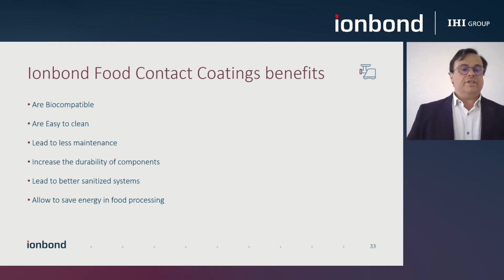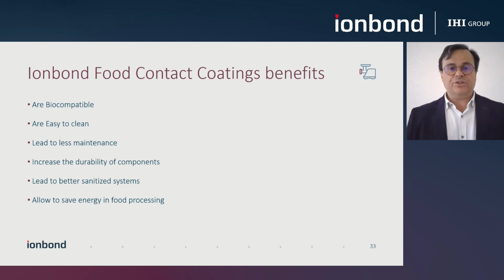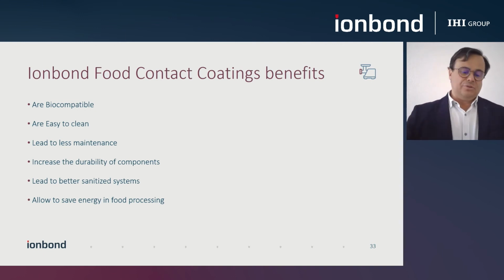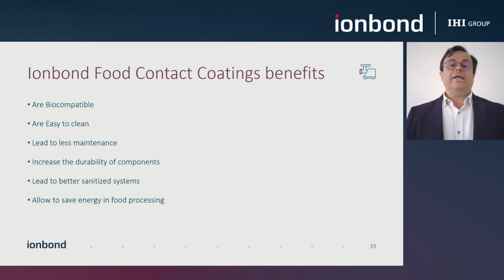In summary, we have seen the coatings are biocompatible, they are easy to clean, they lead to less maintenance in the systems where they are applied, they increase the durability of the components indeed. Overall, you have a situation where you have better sanitized systems where even the bacteriological proliferation is going to be reduced by the use of these inert coatings, which are, as I said already a few times, chemically stable. So overall, we also see the benefit of saving energy because the parts move easier as you have less friction in the systems when they are in contact with each other.